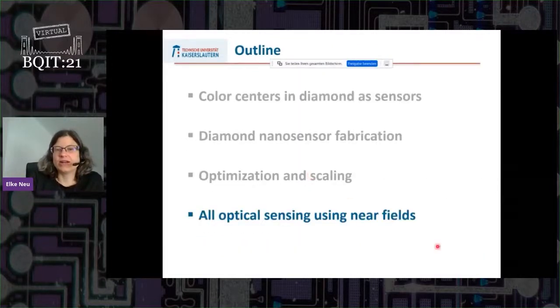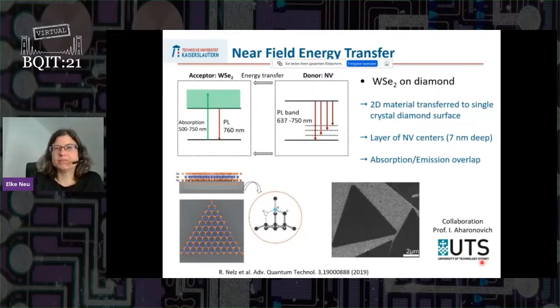Okay, so much for the introduction and the device itself. Now let me show you this novel idea of using the near fields for sensing. And we have chosen here a model system for this FRET transfer. The NV center is the donor and the acceptor is tungsten diselenide. This is a two-dimensional graphene-like material, but it's a luminescent material. And we chose it because we here get the required overlap of the absorption and emission bands that you need for the FRET process. And in collaboration with Igor Aharonovich in Sydney, his group transferred some of these tungsten diselenide flakes onto a diamond, which has a layer of NV centers. And now we want to observe this FRET transfer between the NV centers and this luminescent material.